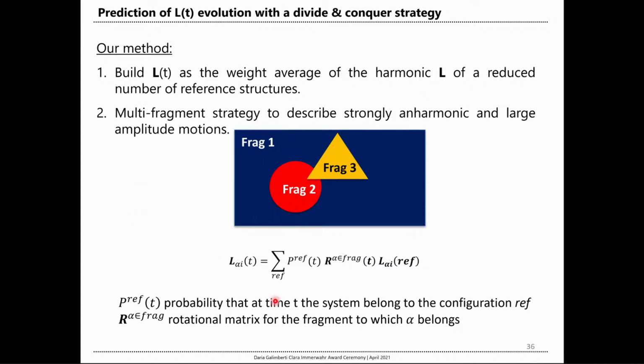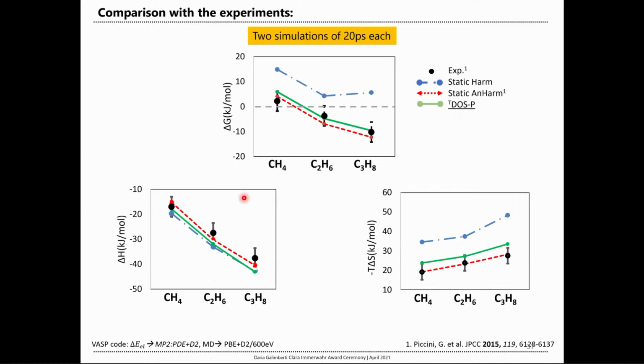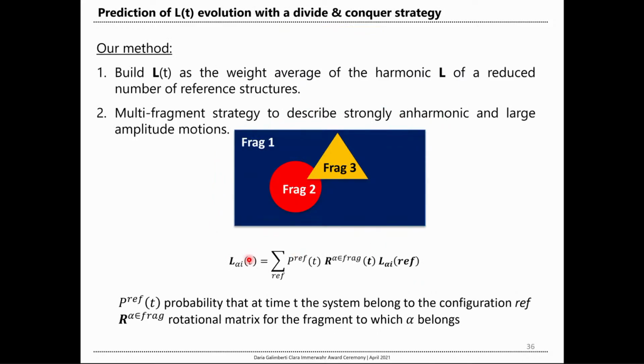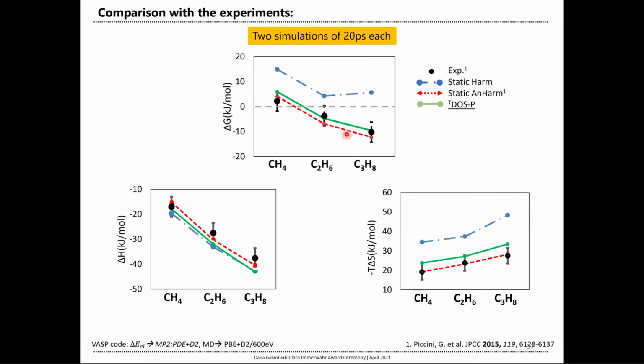And what I want to show you is that this approximate way to build this L matrix is working quite well. And this is how. In this plot, we are coming back to the propane. So the dots are still our experimental values. This is the harmonic approximation, and this red line is the real anharmonic frequency by static calculation. And this green line instead is our vibrational density of states that has been projected on this L matrix built like this. And as you can see, with this simple projection, we are really reproducing the experimental data.